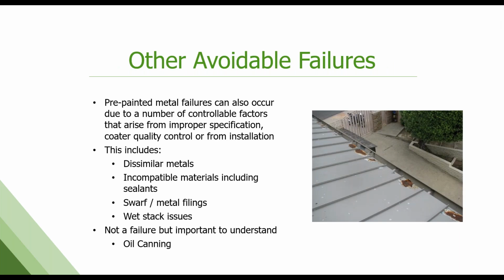So other avoidable failures. Dissimilar metals or incompatible materials being used. Dissimilar metals is the big one, especially in coastal applications, because you get galvanic corrosion. The wrong sealants being used, direct contact with wet concrete is a problem. Swarf or metal filings being left on a panel and not cleaned off. Those little filings are going to rust eventually and leave staining on the panel. Wet stack or storage corrosion issues are a big concern in our industry. This stuff will corrode prematurely if it's left in bundles or stacks without airflow for too long. So you've got to get it up and installed pretty quick.